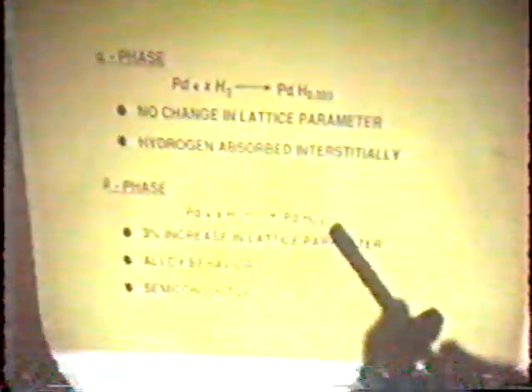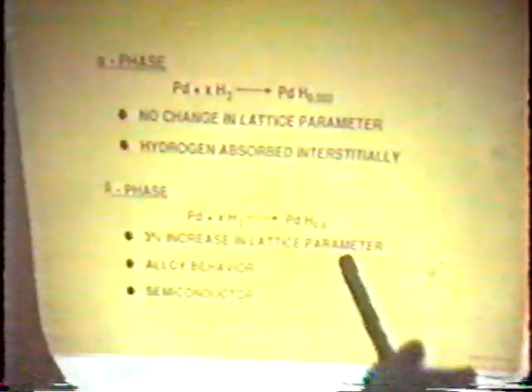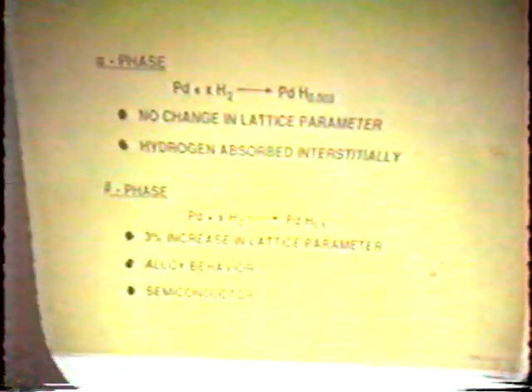And when these deuterons enter the palladium, they first form an alpha phase, but that quickly then goes on to the beta phase. And normally you can load the palladium up to about 0.6 of hydrogen per palladium if you're working with hydrogen. The lattice changes, the lattice expands, becomes more like an alloy and becomes a semiconductor. So there's quite a few changes that go on as you load up the palladium.